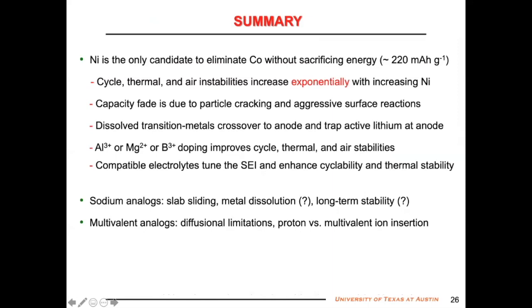Finally, conclusion: nickel is the only candidate that can eliminate cobalt without sacrificing the capacity or energy density, but they have cycle, thermal, and air instabilities that increase exponentially with increasing nickel content. Capacity fade is due to both cracking as well as surface reaction, and dissolved metal ions go to the anode and cause problems. Doping helps, surface coating also helps. Again, compatible electrolytes will also help. When you go to sodium analogs, similar problems can be there.